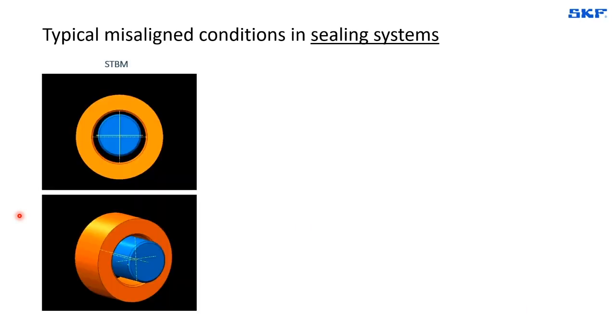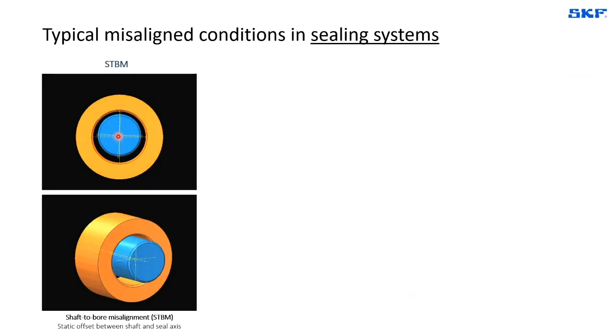In fact, seals are very seldom in static condition, at least for rotating equipment, because they are most of the time submitted to what I call typical misaligned conditions, such as, for example, STBM, which stands for shaft to bore misalignment, where we have a static offset between the center of the shaft, or the rotating shaft, and the center of the seal. In this case, during the rotation, the shaft will continuously run with an eccentricity versus the seal, leading to a tendency, depending on temperature and frequency, to have a higher gap in the area where we have less interference. The interference being the difference between the shaft outer diameter and the seal inner diameter.